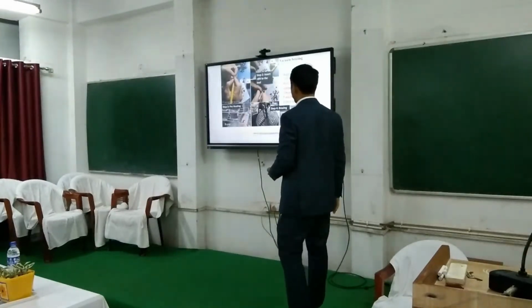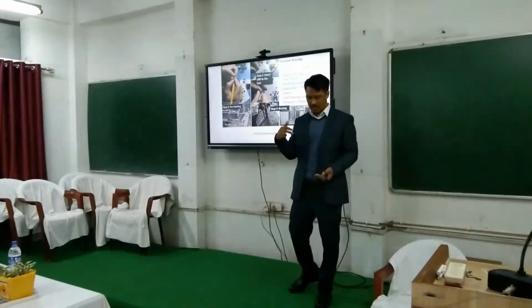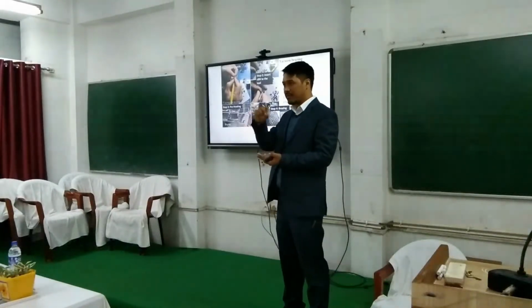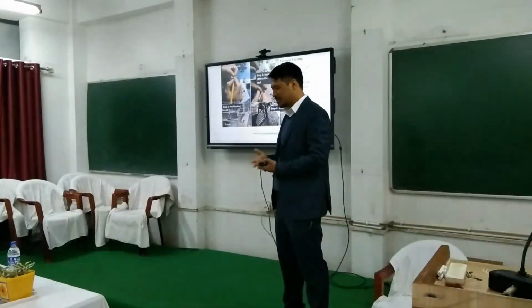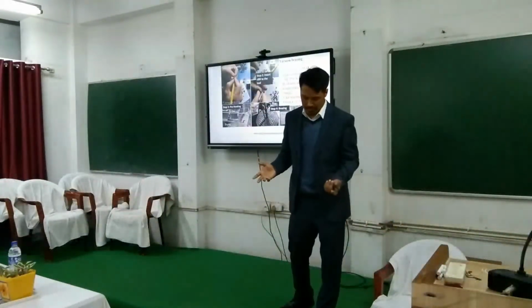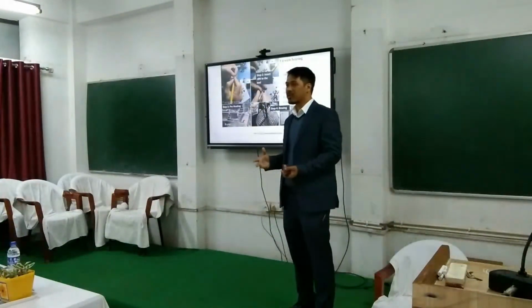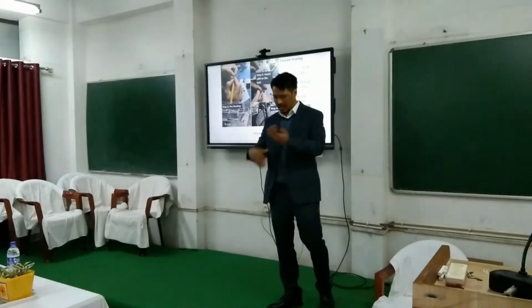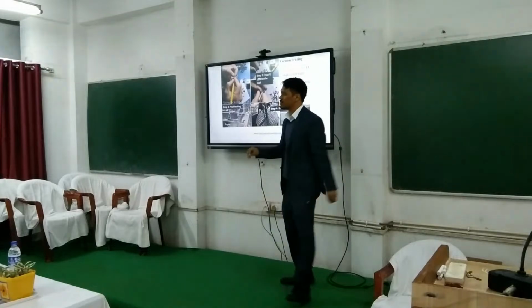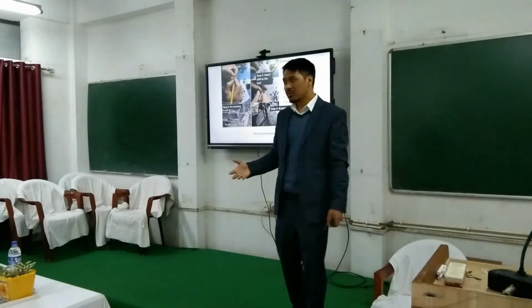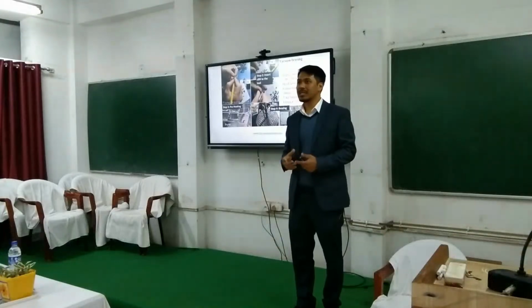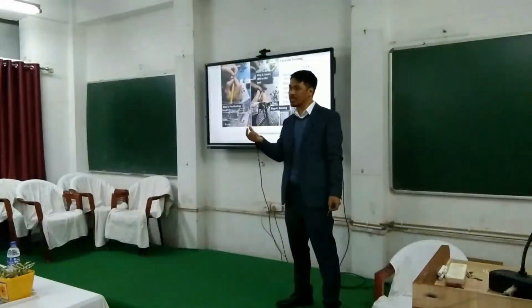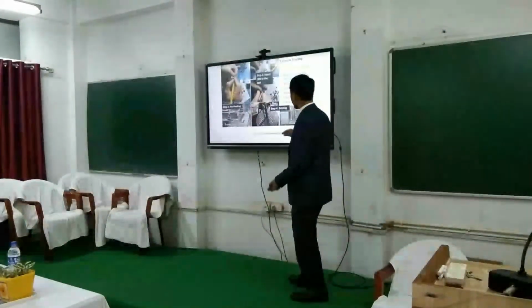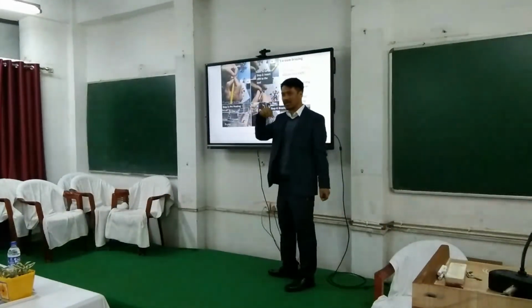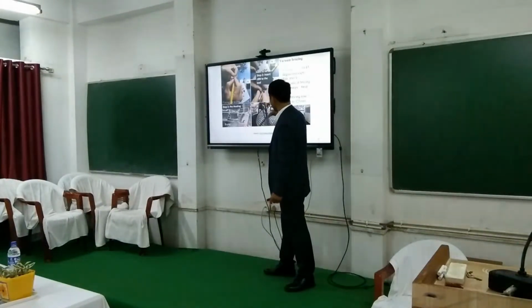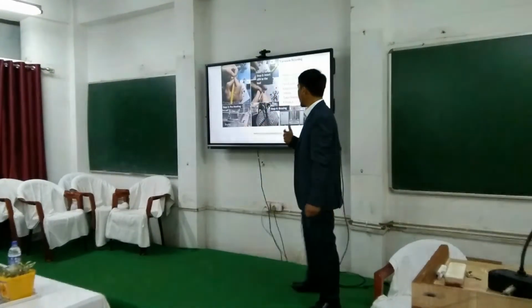The other application is brazing. You already know the tungsten carbide tools which we use. These tools have some inserts. If you want to machine very hard materials like high carbon steel or high strength steel, you cannot machine them with diamond because there is obviously graphitization of diamond. You have to machine them with cubic boron nitride. Cubic boron nitride is also very hard, but it is an expensive material. You cannot make tool inserts fully of cubic boron nitride. So the cubic boron nitride is basically put at the tips of these machining inserts, so that it can be brazed and we can machine this high hardness material.